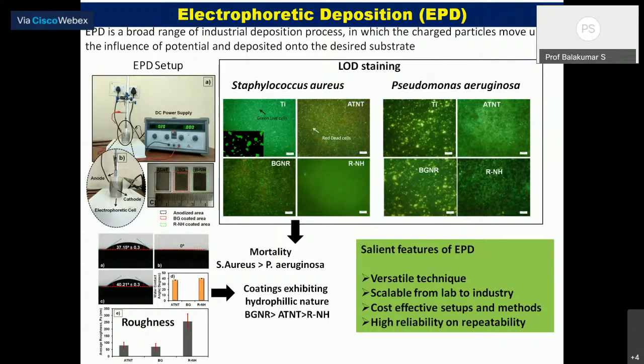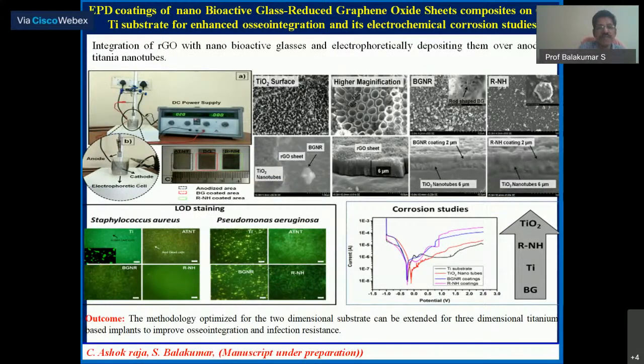There is another way to improve the mechanical properties. Between the titanium platelet and the layer that we are coating, we used titanium dioxide nanotubes that help us improve the adhesion properties. If you look at this curve, it is the titanium platelet, titanium nanotube and layer, giving additional properties and improved corrosion resistance. Biocompatibility is equally good, and it is also possible to change the hydrophilicity and hydrophobicity of the material. Based on your requirement, you can engineer this material. So this is another material that we have developed.